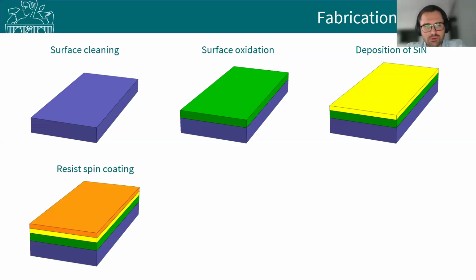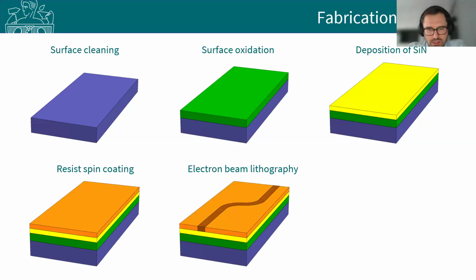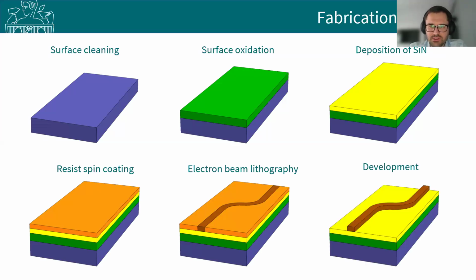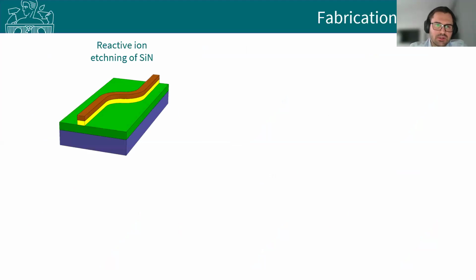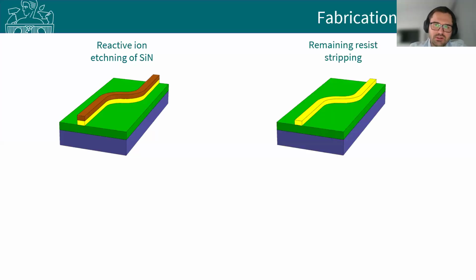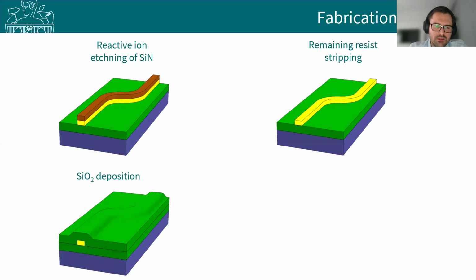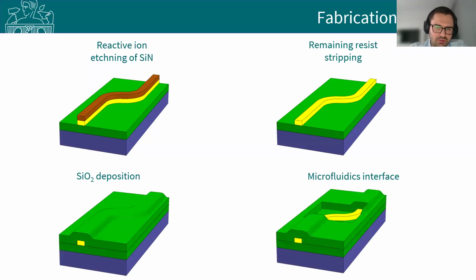After that, resist spin coating for lithography. Next, in our case, it's electron beam lithography, but here it can be done with different lithographies. It can be done, for example, with laser lithography. After that, there is a development, so we have the proper pattern in the resist layer. After that, reactive ion etching of silicon nitride, remaining resist stripping, then silicon oxide deposition.